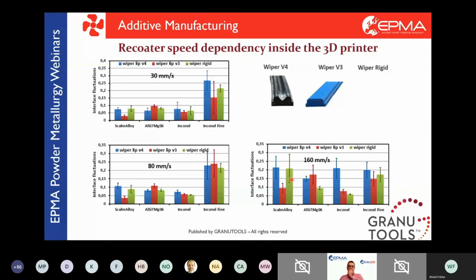When we go at 160 mm per second, we can see that the differences are big, and therefore the wiper must be taken into account. So if you want to spread your powder at 30 mm per second or 80 mm per second, you can just use the rotating drum principle to characterize your powder. You will get a good idea on spreadability. You can set up a pass-fail test, and you can compare powders and sort them from more spreadable to less spreadable without having too much issues. This will not be a problem.